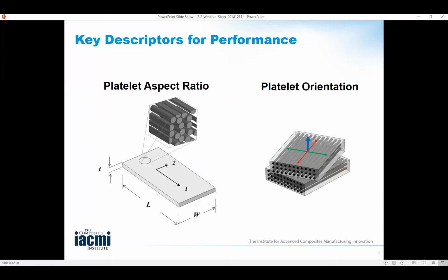As you can imagine, then, fiber volume fraction is key, as is the platelet aspect ratio, to understand the geometry of the platelet as well as the platelet orientation. Those will have critical measures on the performance of the as-manufactured part. And the good news is that we have models to treat all of these: the fiber volume fraction, the aspect ratio, and the platelet orientation.